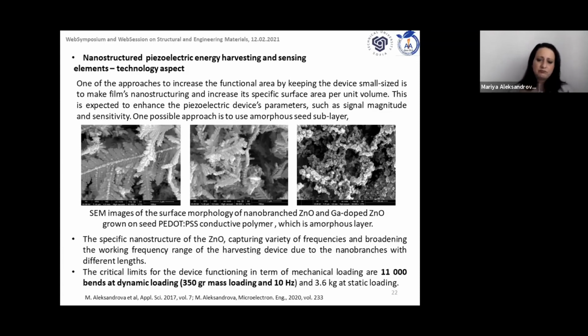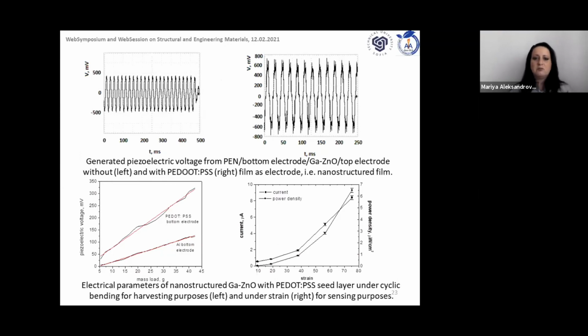Well, here the advantage is that the different geometrical sizes available in this nanostructure are able to capture a variety of frequencies and broaden the working frequency range of the device, which is not possible when you use a dense film. In general, the voltage could be increased by almost 300 millivolts, which is also an advantage when we compare with a high density layer, which is not structured.